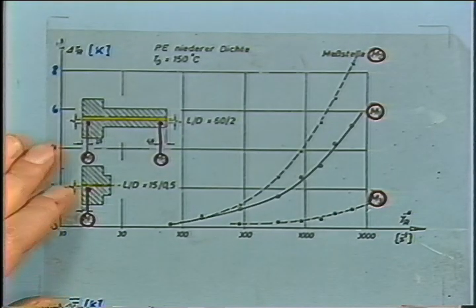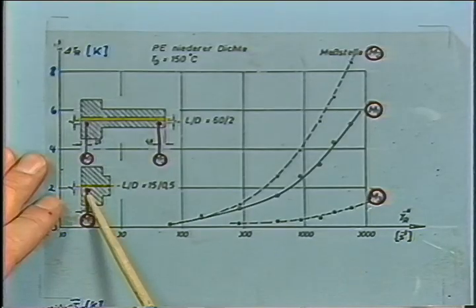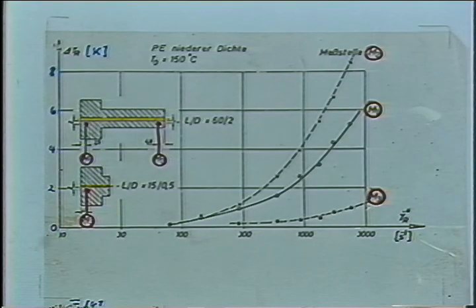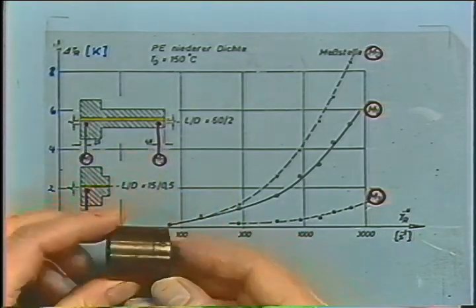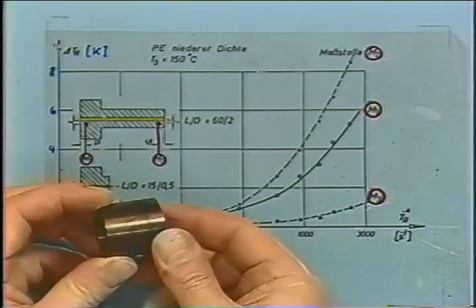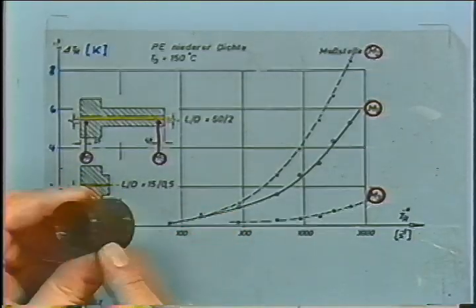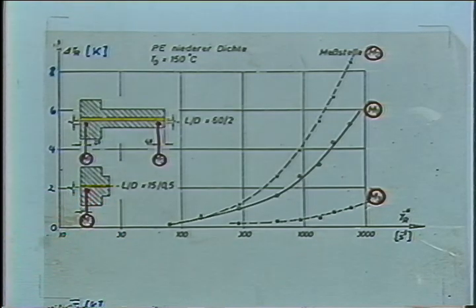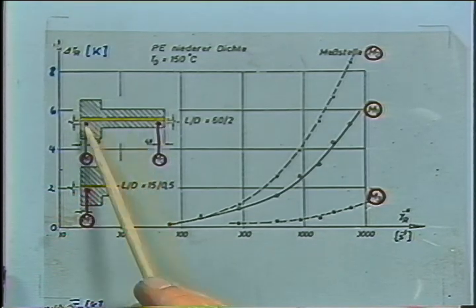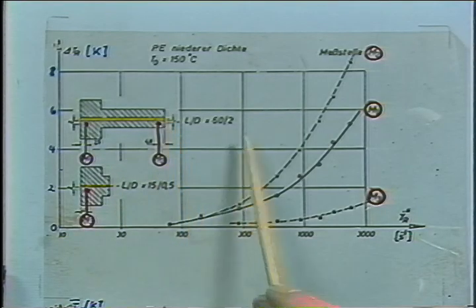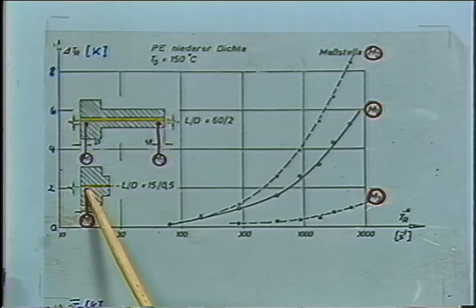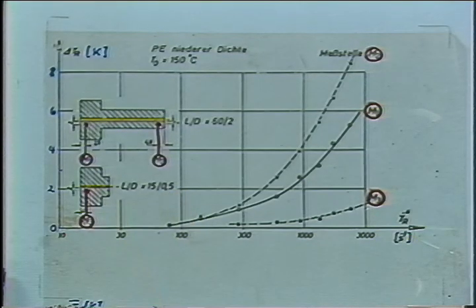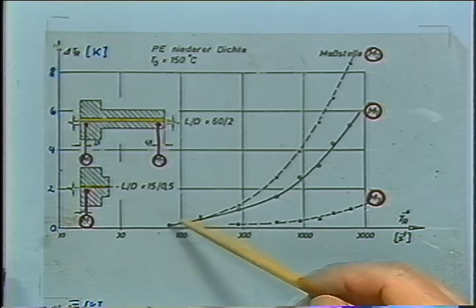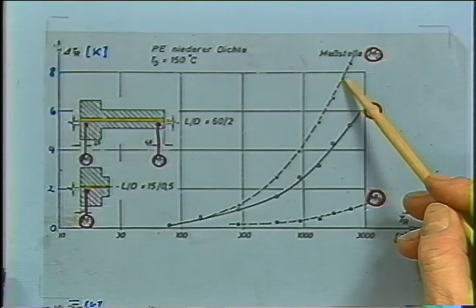Here we simply put a thermocouple in little capillaries. You know, in capillary rheometry, one often uses very, very small dies, and mounts this onto the reservoir. Here you can see it's hollow in the back, so it's really a very, very short capillary. And in this capillary, we mounted thermocouples at the beginning and at the end for the bigger diameter. This is a 2 millimeter capillary, and just one thermocouple for the 0.5 millimeter diameter. Now, the temperature reading as a function of the shear rate goes as follows. With increasing shear rate, the temperature in the wall will go higher and higher.